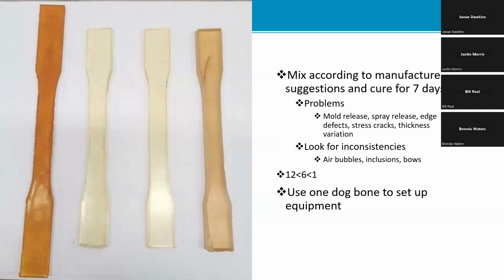Now, what you do is you're going to make 12 dog bones, is what PennDOT does. We make 12 dog bones because, again, things go wrong with the 12 dog bones. You want to pick out your best 6 dog bones that you have. And with those 6 dog bones, one of them is going to be used to set up the equipment. So that's very important. You want to make 12, pick your best 6, and you want to use the best one or either one of those 6 to set up your equipment.